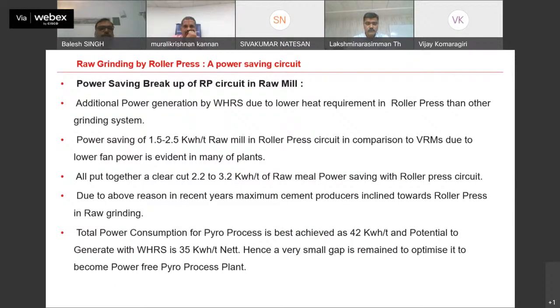So what it attracts: the power saving breakup of RP circuit in raw mill, additional power generation by waste heat recovery system, power saving of 1.5 to 2.5 kilowatt in raw mill in roll press circuit in comparison to other grinding circuits. All put together, a clear-cut 2.2 to 3.2 kilowatt per ton raw mill power saving in roll press circuit. So due to all these above reasons, it has become very popular in recent years.